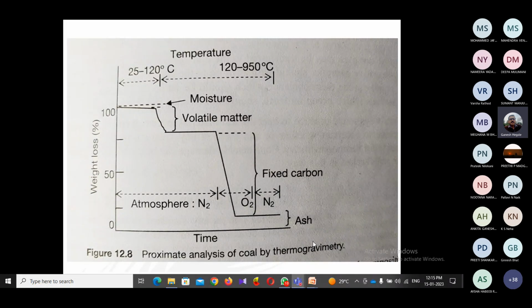That is, what all things you come to know. So you come to know what the moisture content of the coal is. Okay, if the coal has a very heavy moisture content, you find a lot of dip here. That indicates the coal is not very good for heating purposes, because in order to make the coal catch fire, the preheating requirement is more if the moisture content is more. So you can decide how much temperature or heat is to be supplied to the coal to make it catch fire.